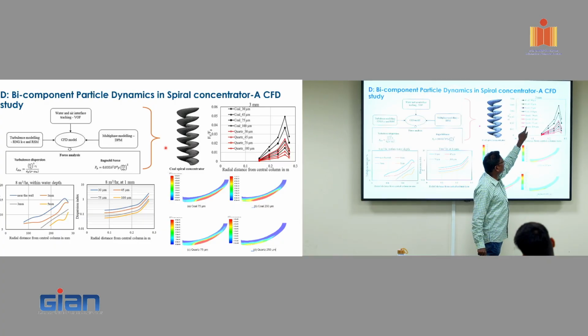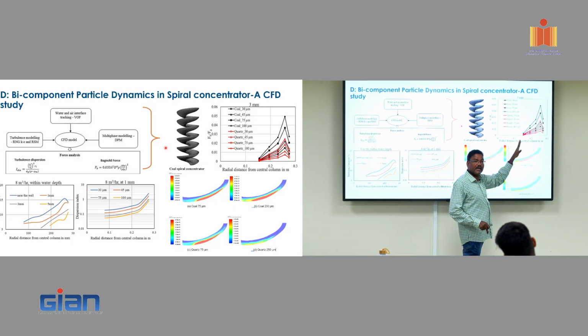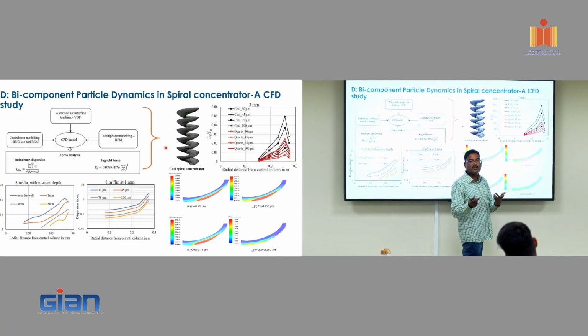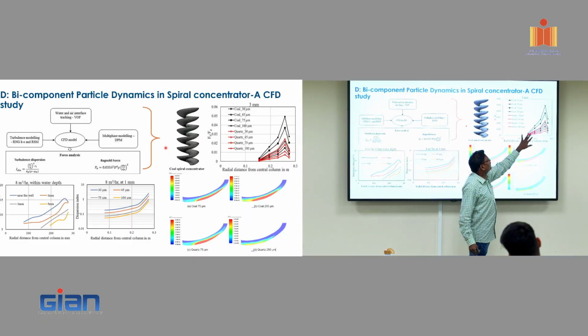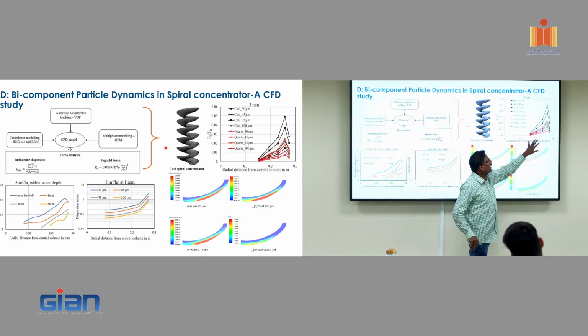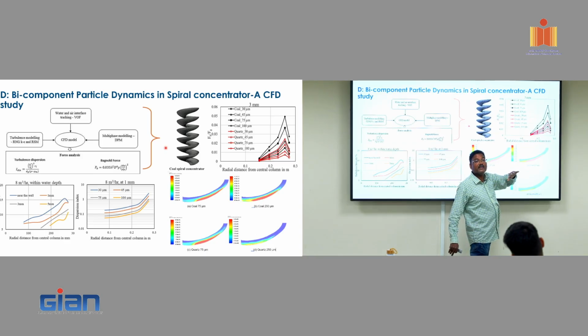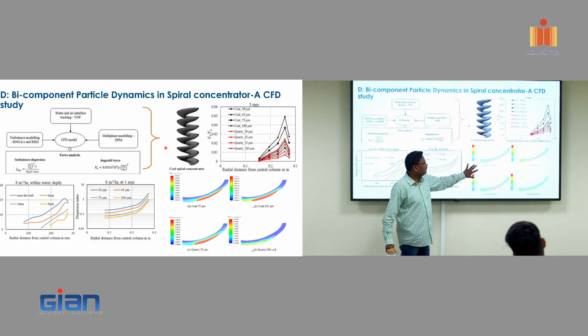You can clearly see that the coal particles, in terms of the influence of gravity, are influenced less compared to silica. Obviously, there is a mass difference and a density difference. So silica would typically settle to the bottom layers, and the coal would try to settle everywhere, including in this picture. You can see the same notion here.